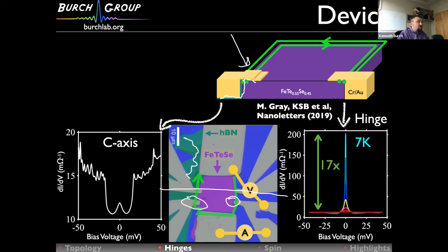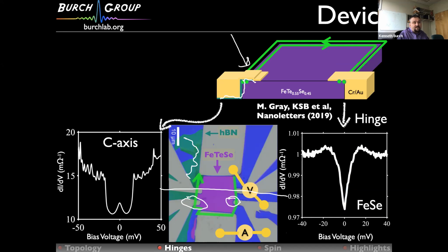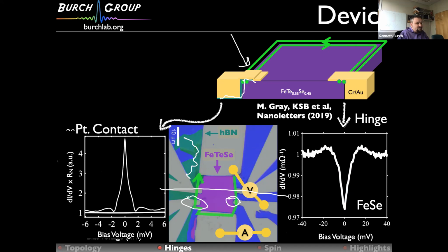And we also did some more controls. So we tried iron selenide, which is not meant to be topological. We actually never even got Andreev reflection there. I never quite understood why, but admittedly we didn't try that hard. We tried point contact measurements, which also would repeatedly show these nice zero bias peaks. And we think there it's just that when you cleave it, you have many hinges. And so that might be why, when you contact something that doesn't have a nice flat surface, you see this hinge response.